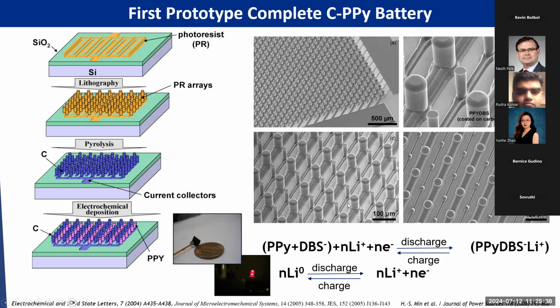One is bare carbon, glassy carbon. You can see the diameter of this carbon is much smaller than the very broad ones. Those are polypyrrole coated on the bare carbon posts. We basically used an electrochemical polymerization method to deposit polypyrrole on one set of the bare carbon posts. Then we create the anode and the cathode. Carbon is the anode and polypyrrole, a conductive polymer, we can use as a cathode. It's not the best battery setup, but because of the simplicity of electrochemical deposition, we can deposit conductive polymer very easily on the carbon post. So we adopted this recipe.